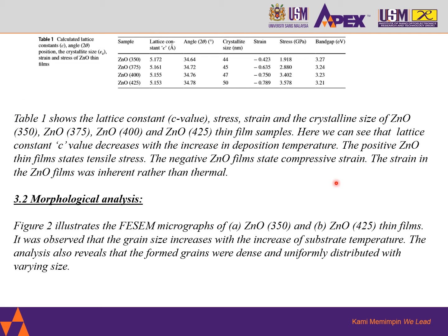Here we can see that the lattice constant C value decreases with the increase of the deposition temperature. As the temperature increases, the lattice constant value C decreases. The first one is 5.172, then it decreased to 5.161, then 5.155, and then 5.153.